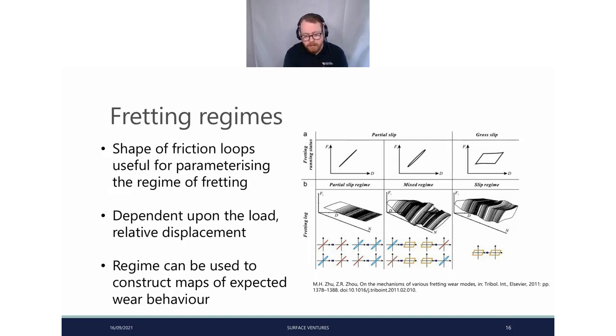We can then get mixed regime, where we're moving between gross slip, which is the highest amplitude of this, typically with the highest amount of friction, and partial slip, so transformations between these processes. This is probably where we're getting the most interaction between the different elements. So friction could increase dramatically, so we drive the displacement down.